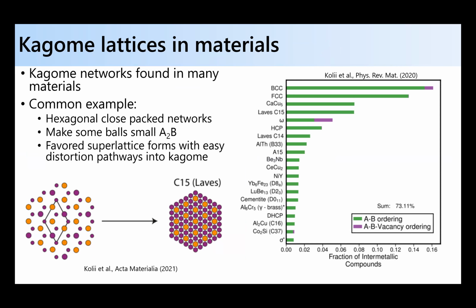The reason is that if you look at intermetallic compounds, and materials scientists have known this for a while, if you just think about hexagonal close packed balls in some AB stacking, and you replace 1/3 of the balls with much bigger balls, then sterically, the way they want to pack is in layers. They want to basically form a supercell that's alternating layers of a kagome network and triangular lattice. The way those layers alternate along the z-axis forms a variety of very common intermetallic types. If you look at this histogram of known intermetallic phases, like the calcium copper 5 and the Laves phases, some of the fundamental units which comprise those structures are kagome networks of metal ions.